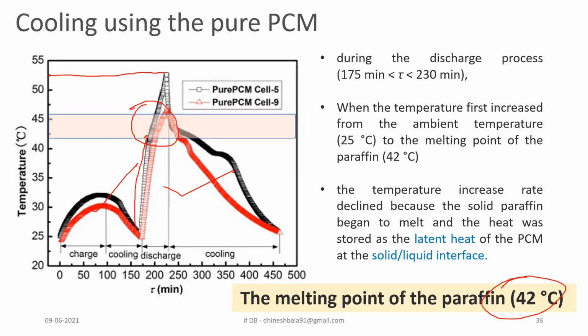So for that, you need to give a constant temperature heat addition to the system. Most of the heat would be trapped by the PCM and it won't be liberated to the system. So that is the reason why there is a drop in temperature as compared to the previous case. Here you can just see the temperature has fallen below 55 degrees Celsius as compared to the previous case of 65 degrees Celsius. So in the previous case, the temperature rise was above 65 degrees Celsius. But when you incorporate a PCM into the system, most of the heat is required for the conversion of solid to liquid phase.